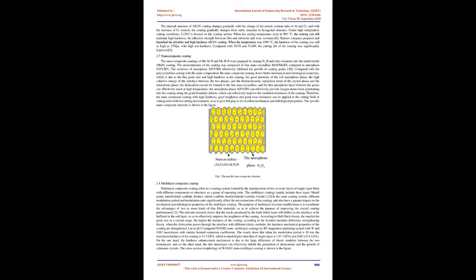The purpose of multilayer structure modification is to coordinate the advantages of two or more kinds of thin film materials, so as to achieve the purpose of improving the overall coating performance. [12] The relevant research shows that the cracks produced by the hard brittle layer will deflect at the interface or be buffered in the soft layer, so as to effectively improve the toughness of the coating. According to Hall-Petch theory, the smaller the grain size in a certain range, the higher the hardness of the coating. According to the Koehler modulus difference strengthening theory, when the dislocation passes through the interface with different elastic modulus, the hardness and mechanical properties of the coating are strengthened.